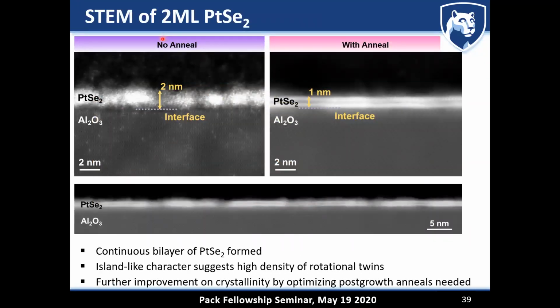And indeed, what we found was that for the unannealed platinum diselenide films, to state it politically incorrect, we have pretty much garbage. There's a lot of islands and not very crystalline materials. But as we do the anneal, you can see how a bilayer of platinum diselenide is forming. And this is really not just in one spot. You can take relatively large scans of scanning transmission electron microscopy. You can see that a continuous bilayer of platinum diselenide is really formed.